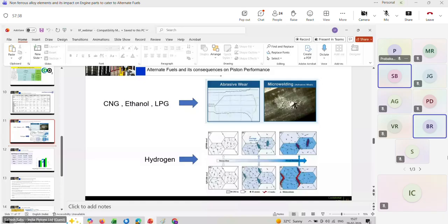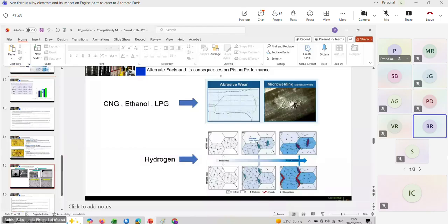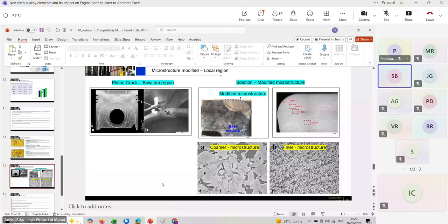Similarly, the bowl rim that you are doing, do you do any test after the casting is done, after the machining is done on the bowl rim? See, after machining is done on the bowl rim, it is normal that, to ensure the strength of the part, it is typically checked only in engine testing. Okay, so engine testing is the final location. Before engine testing, we do have similar tests like UTS and hardness measurement, all of which come into the picture.